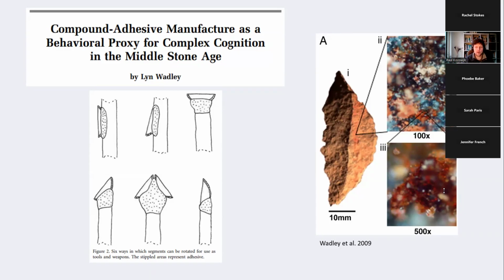So these South African adhesives are typically not quite as old as birch bark tar. The oldest of these is around 60 to 70,000 years old. It still puts them firmly in the Middle Stone Age and contemporaneous with some of the other birch bark tar finds. With these compound adhesives, the question of how they were doing it was not such a mystery. They were mixing together these ingredients. Why they were mixing them can also be explained by performance. Mineral fillers such as red ochre tend to improve the workability and strength of these resin-based adhesives. The real question being addressed here, and what we're getting to with the tar, is what it means for the human behavior and evolution behind the production of these adhesives.